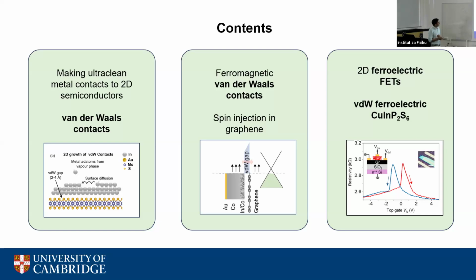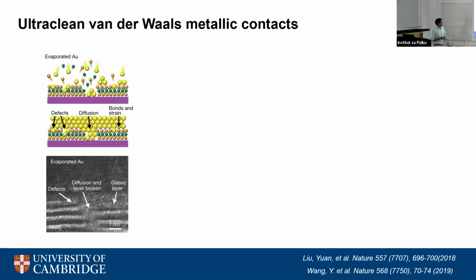So the first thing, why do we need good contacts? We have a schematic here of a monolayer TMD, like MoS2 or WS2. When you evaporate gold or titanium or chromium, all these metals, using electron beam evaporation or thermal evaporation, this is a nice scheme from Shangjian Duan's group, they show that you really create a lot of damage, because these are energetic ions which get evaporated and have high kinetic energy. And when they hit the surface of this one-layer molybdenum sulfide, you naturally create a lot of defects.